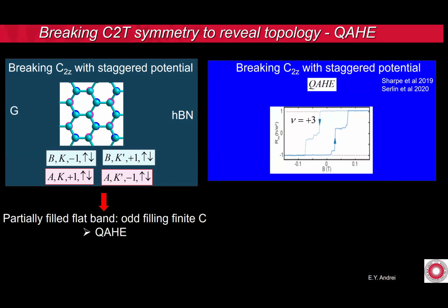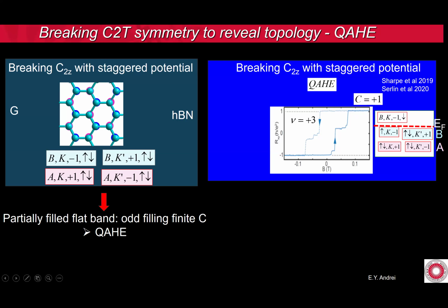It doesn't care. It has the same energy. So if you look at the sample, you won't see an anomalous quantum Hall effect. But if you break this symmetry by applying a magnetic field, so let's say you apply a positive field, then it's going to like to align so that the pseudomagnetic field aligns with the external field, and now you read a Chern number of +1.